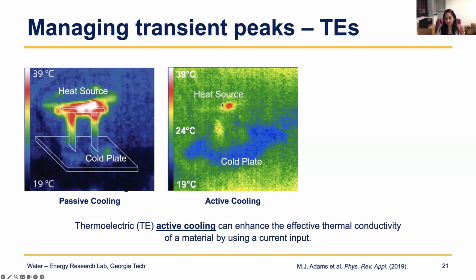When we turn on the thermoelectric by providing a current to it, you immediately see that most of the temperature is actually dissipated. So the highest temperature now is closer to 24 degrees Celsius, except where we have the heater itself, right? So this is the same heater at 39C, but you can see where the thermoelectric is actually a lot colder. So this is active cooling, and it's not using typical bismuth-telluride semiconducting thermoelectrics. We're using metallic thermoelectric materials. So you're using a current to move more heat, but in the natural direction from hot to cold. So not refrigeration, but active cooling.